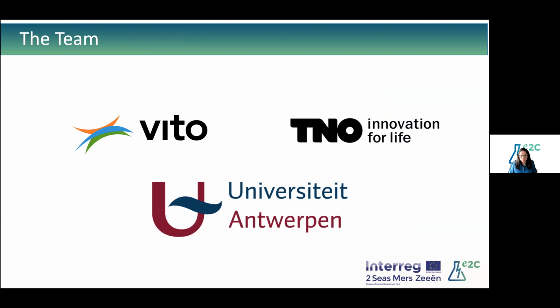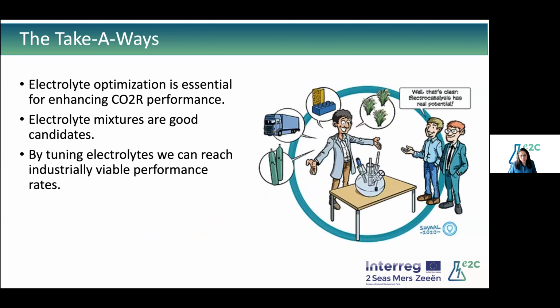The team here is working in close collaboration with VITO, TNO, and Antwerp. We're doing the electrolyte analysis, while the other institutions are working on development of the cells and also the catalysts. The major takeaway of our end of the research is that electrolytes have a very large role in influencing CO2 performance. And when you have mixtures, in this case a ternary mixture, they are a good candidate that could improve this production. In the end, we can lead to an industrially viable system if we tune the electrolytes to optimize it in an easy and low-cost manner.